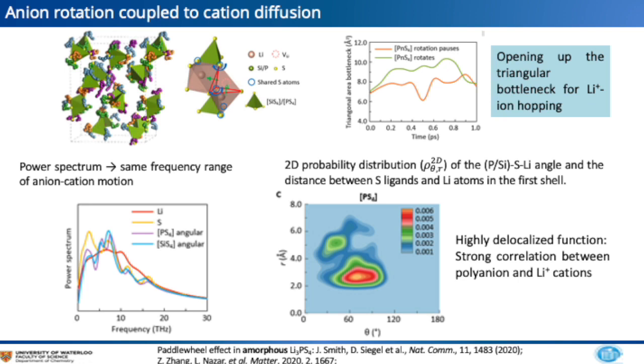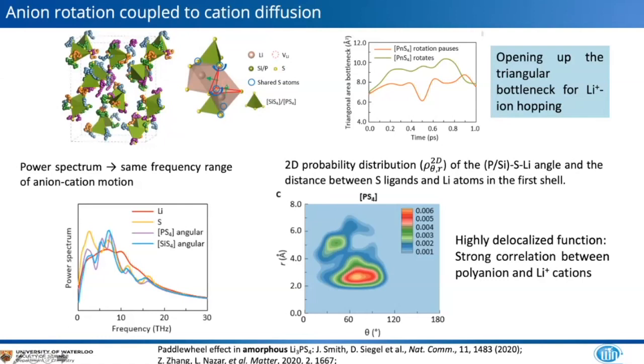And the 2-dimensional probability distribution of this phosphorus to sulfur to lithium angle and the distance between the sulfur and lithium atoms in the first shell also shows the same sort of effect. Effectively, that shows that the groups are highly delocalized, which signifies a strong correlation between the polyanion and the cation. If there was no correlation between polyanion mobility or rotation and the lithium, we would simply see this localized in a discrete spot. So the fact that this is delocalized is evidence of this correlation.